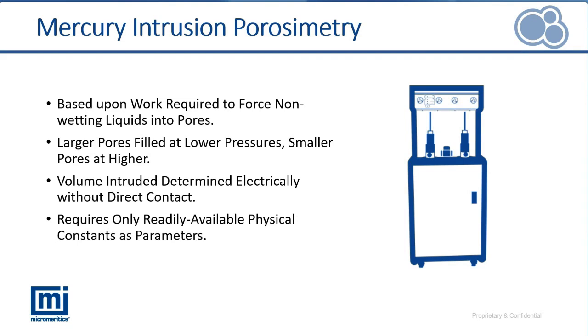Determining the amount of mercury, the volume of mercury intruding into the pores, is a little bit tricky at first, or it could be. We want to do it without any direct contact with the mercury, so we're going to do it electrically, and we'll explain how we use capacitance to determine the amount of mercury that has moved into the pores. This analysis only requires readily available physical constants as parameters, as we'll see when we look at the calculations for determining pore size distribution from the combination of pressure being measured and capacitance measurements.